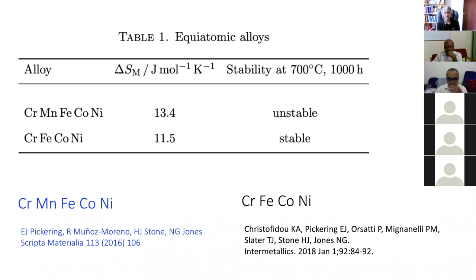Now, the other issue is, we are assuming an ideal entropy of mixing. That means that the atoms are distributed at random. Now, there is a technique to study whether or not the atoms are distributed at random, and that's the field ion microscope and atom probe. And I'm going to show you, so the field ion microscope and atom probe can see individual atoms in the structure and also chemically identify them. So we can do atom by atom analysis.